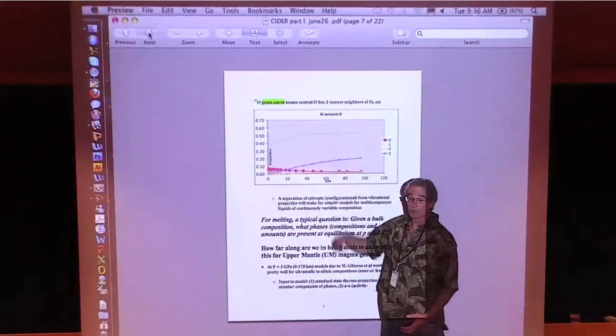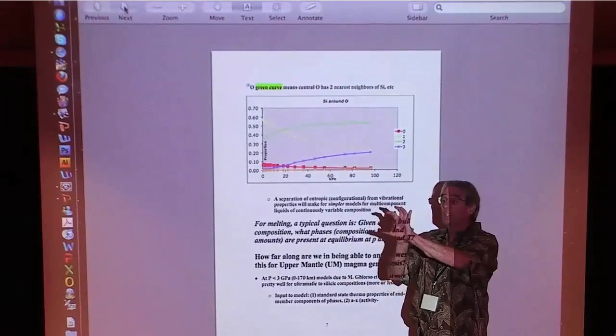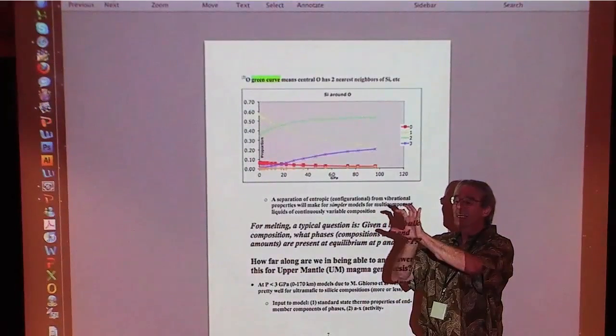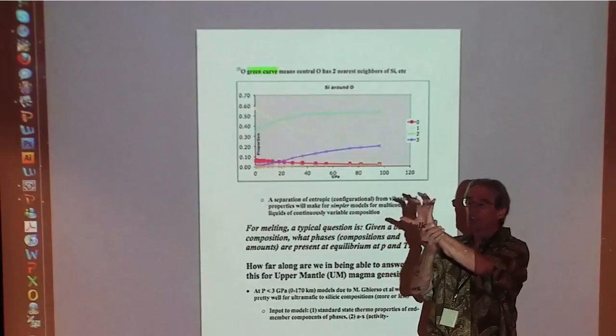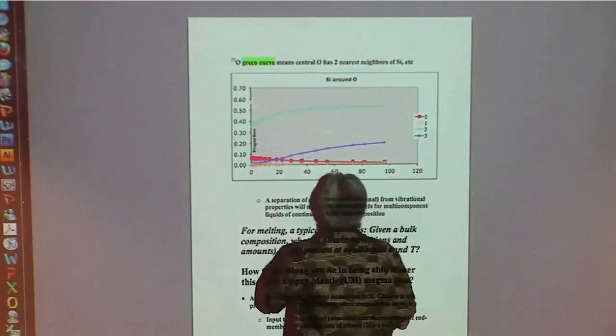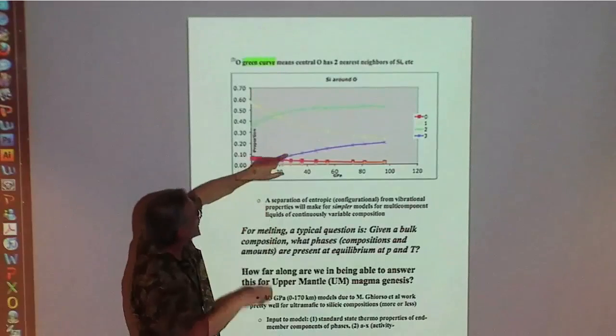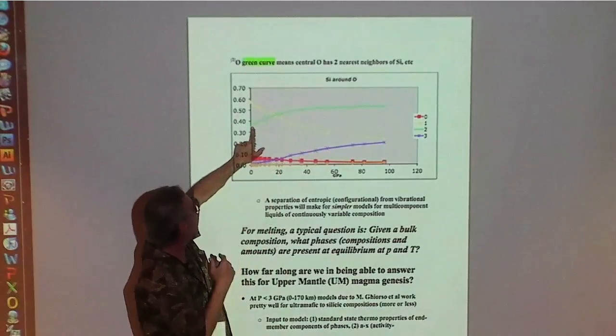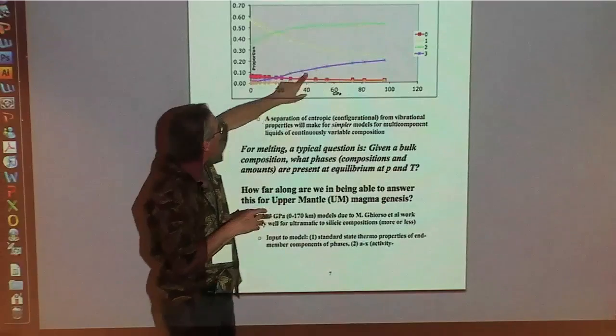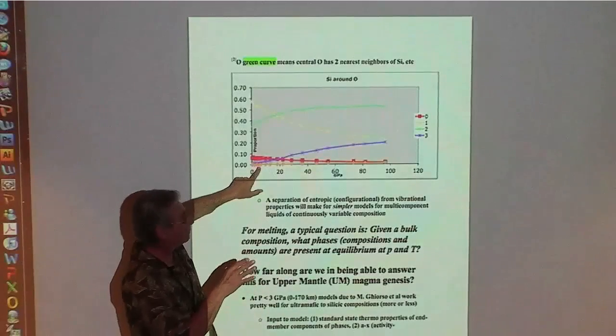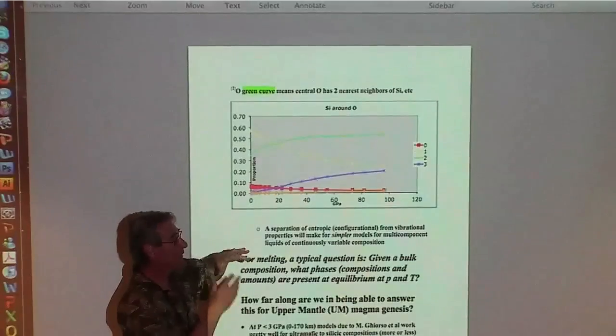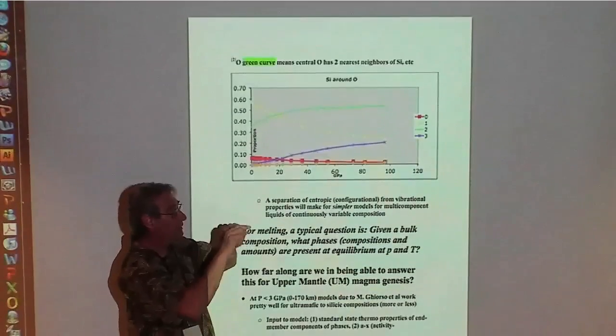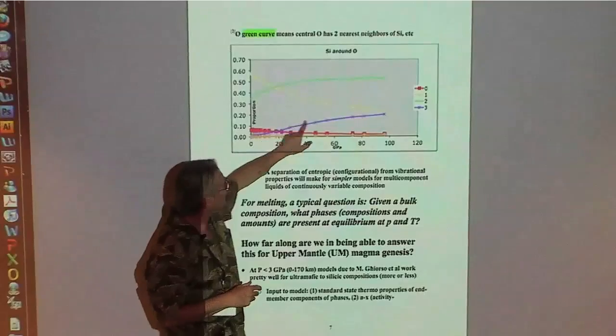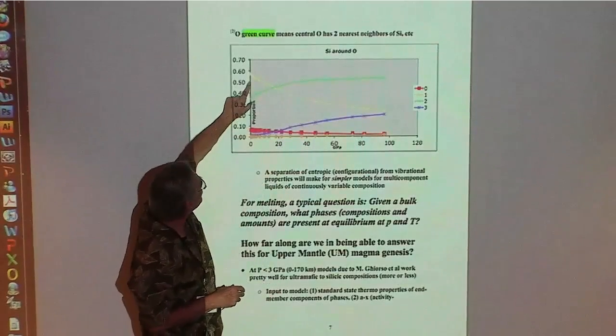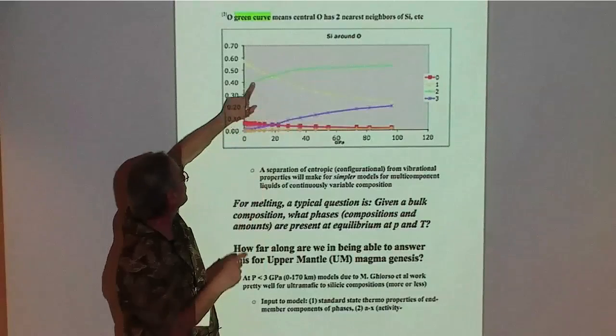Here's another way of looking at it. This is the Si around O. So now you take O as your central atom, and you say, how many Si atoms are nearest neighbors to this central O? What fraction of these O atoms have 2 Si as nearest neighbors? That's that. What fraction of these oxygens have 3? Ooh, that's the structure of stishovite, actually. Every oxygen has 3 nearest neighbors of silicon. Every silicon has 6 nearest neighbors of oxygen. That's increasing, right? And what fraction of the oxygens have 1 nearest neighbor of silicon?